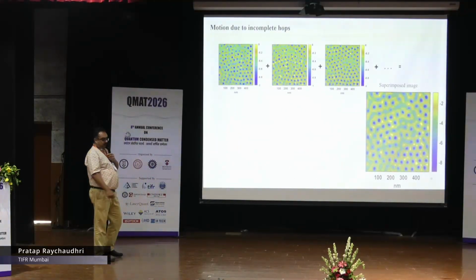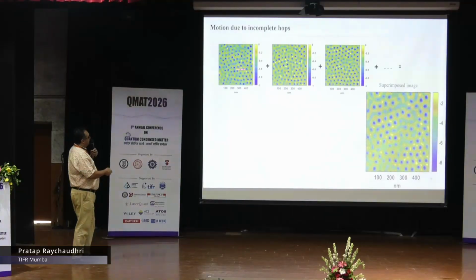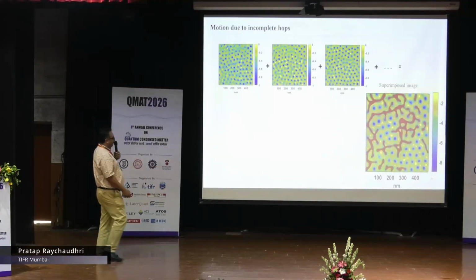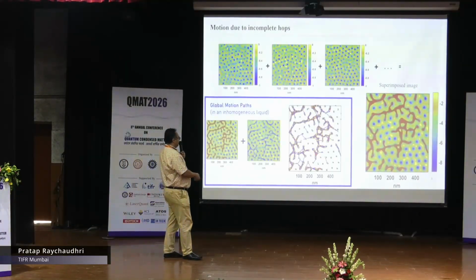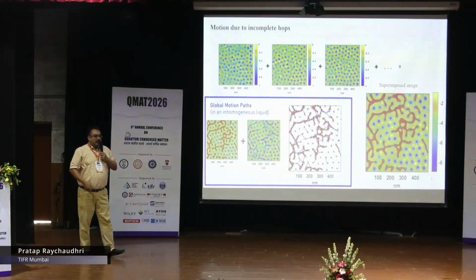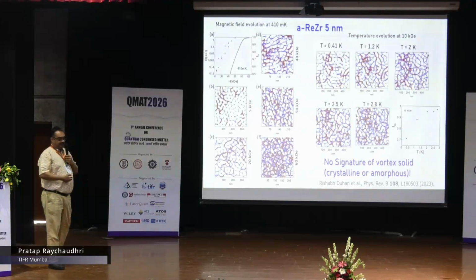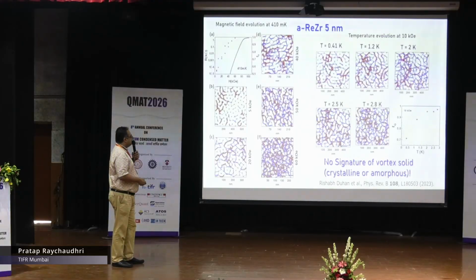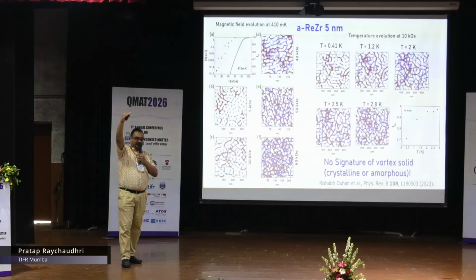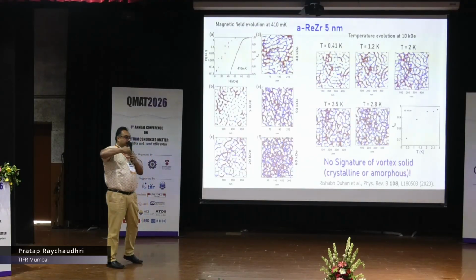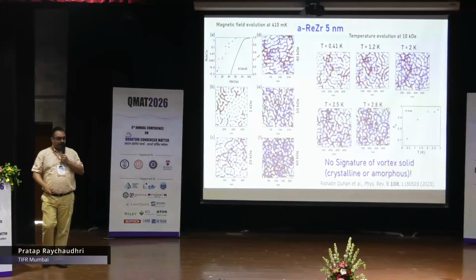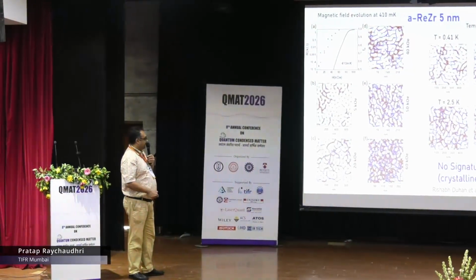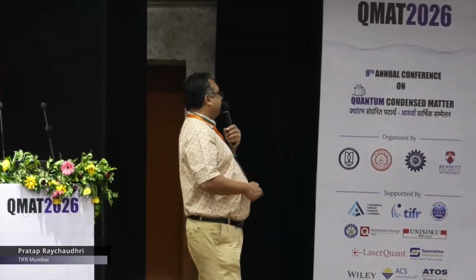Now these incomplete hops also result in motion, and to find that, you take all these images and you sum them. And then you can see now these motion paths from incomplete hops. You can again join them using some criteria, and this is your overall motion path, which consists of both complete and incomplete hops. Now when you do this as a function of temperature and magnetic field, the message is that even when we have increased the pinning energy, because your thermal fluctuation is large enough, we do not see a vortex solid anywhere, neither crystalline nor amorphous. We are always in this very inhomogeneous liquid state.